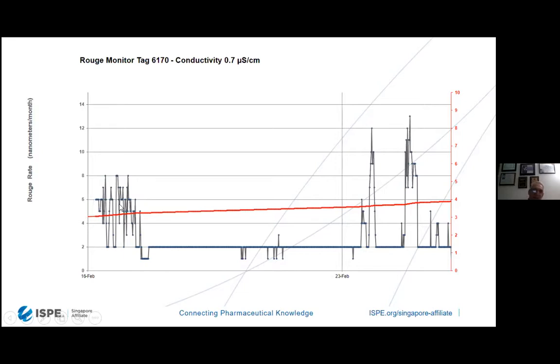And what you're looking at, if you were looking at the mean of this data, it would be very flat, which is shown by the data over here on the left. Over here, at this point, you can see instead of running between 4 to 5 nanometers, all of a sudden we're below 2 nanometers. And the interesting issue is why?